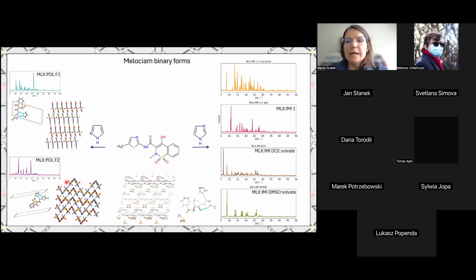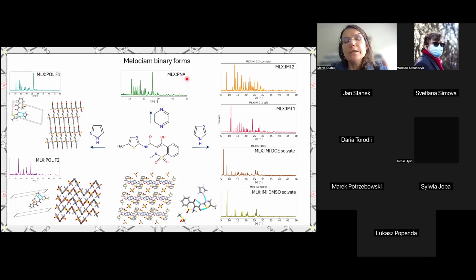polymorphs. Then for a second coformer, we obtained actually 6 different crystal forms, binary forms or tertiary forms, so containing another component. In this case, this was a solvent molecule in different ratios. So this was actually a very complicated landscape. And finally, one co-crystal for meloxicam and pyrazine. So for this variety of forms, actually only for 3 of them, we got single crystal X-ray diffraction results, despite many, many efforts to get some more.